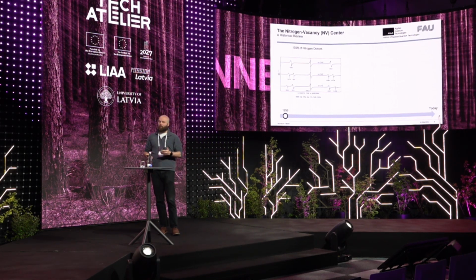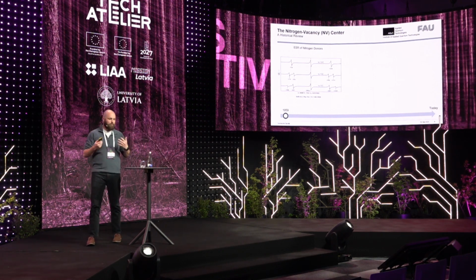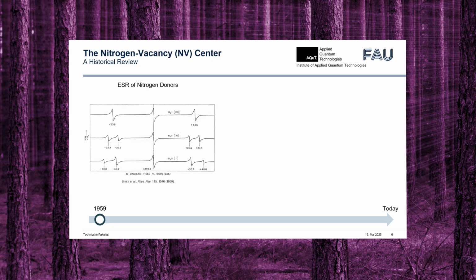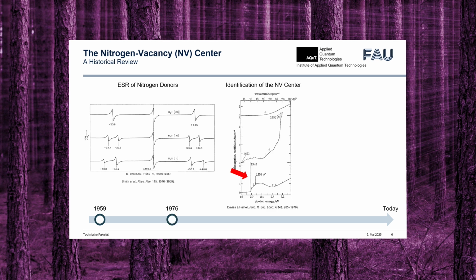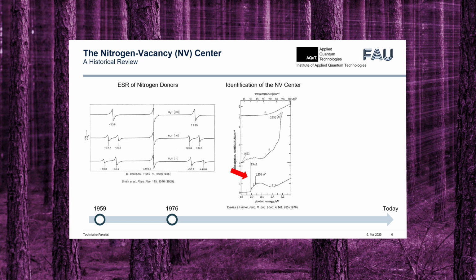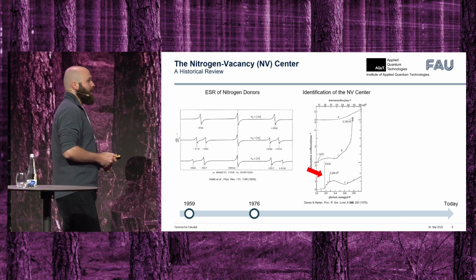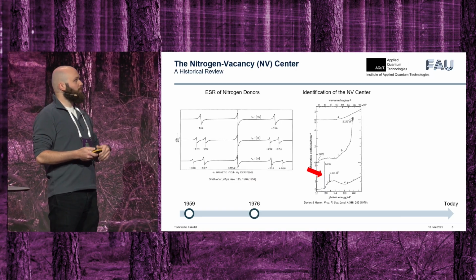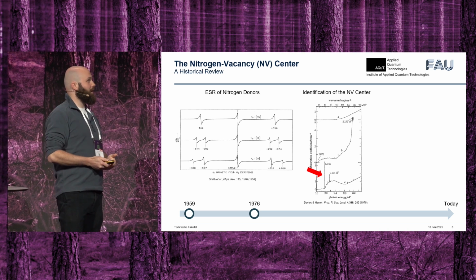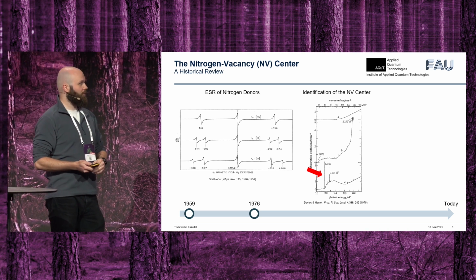From the 1950s, when the first electron spin resonance experiments showed microwave radiation being absorbed by the diamond, which revealed a nitrogen donor in the diamond lattice, which we now know is the most abundant paramagnetic defect in diamond. It took 20 years for researchers to find what is now defined as the NV center by its very distinct emission band after irradiating and annealing and creation of these NV centers.